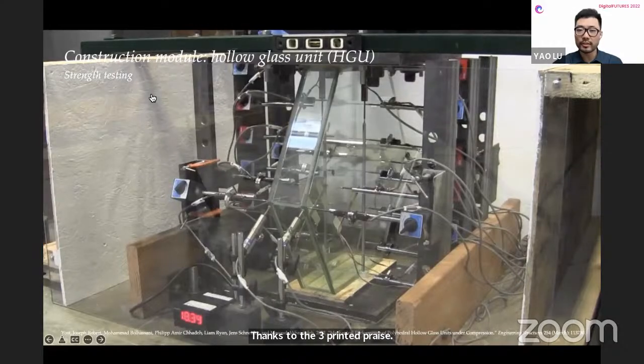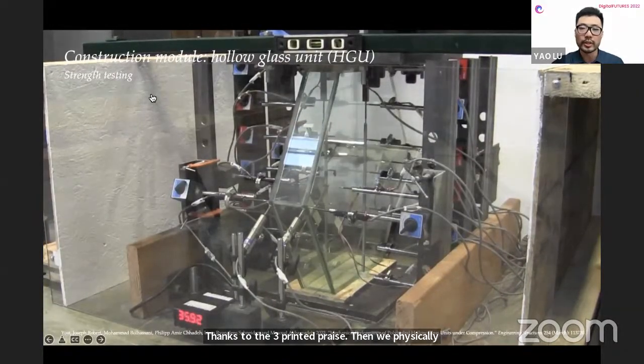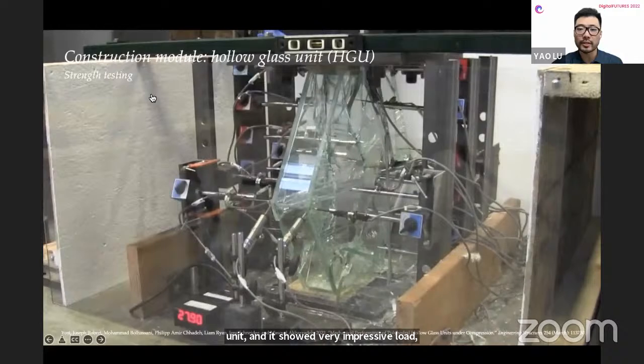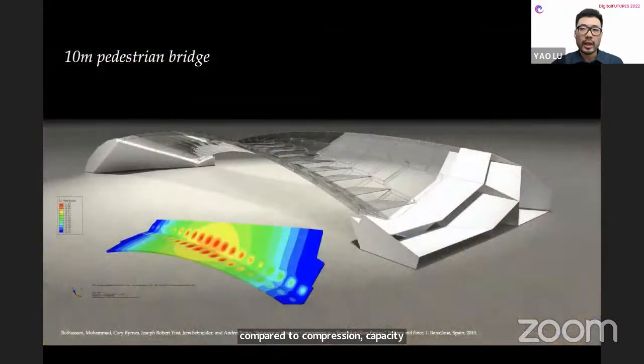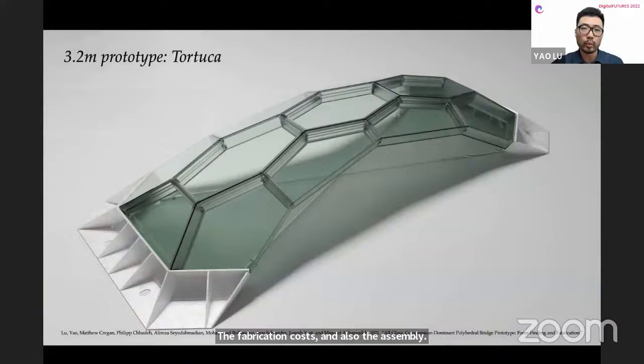Then we physically tested the mechanical performance of this hollow glass unit, and it showed very impressive load-bearing compression capacity. As Masoud just mentioned, we've shown that it's totally possible to make a 10-meter pedestrian bridge using this construction unit by leveraging the compression capacity of the hollow glass units. But we still need to deal with the detailed design issues, the fabrication constraints, and also the assembly logic issues. And therefore, we introduced this smaller scale prototype called Tortuca.